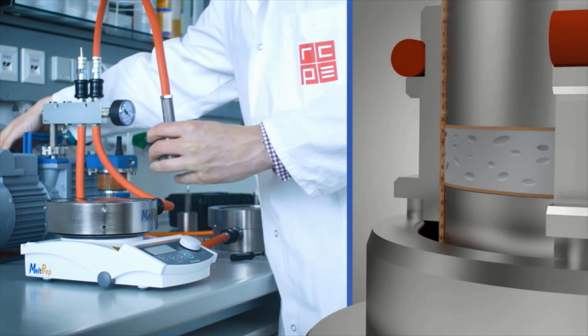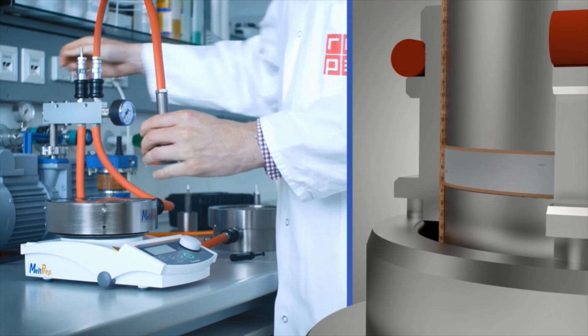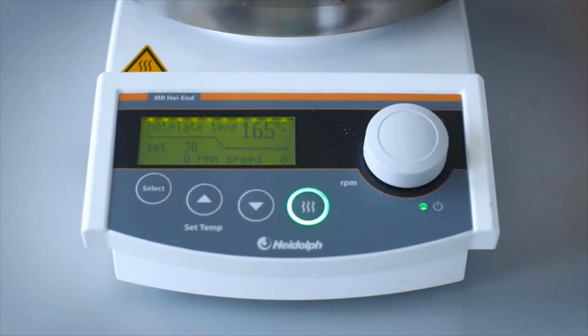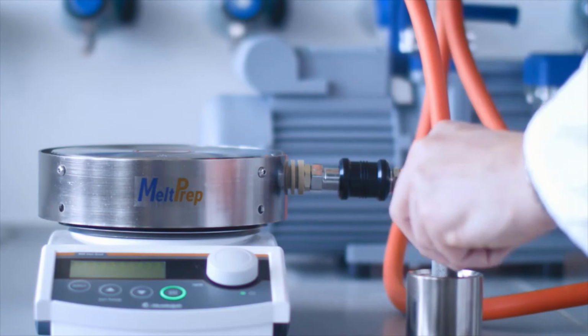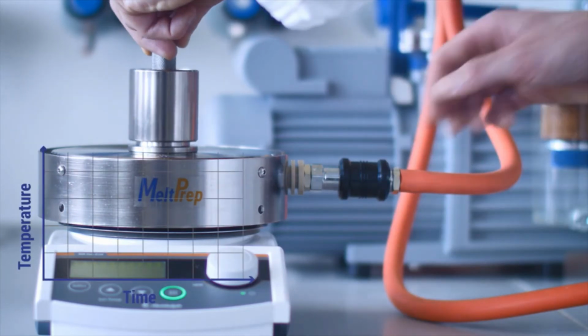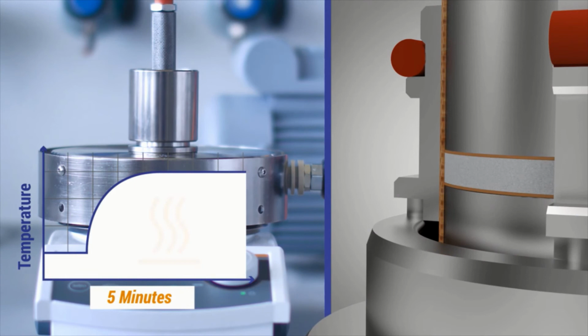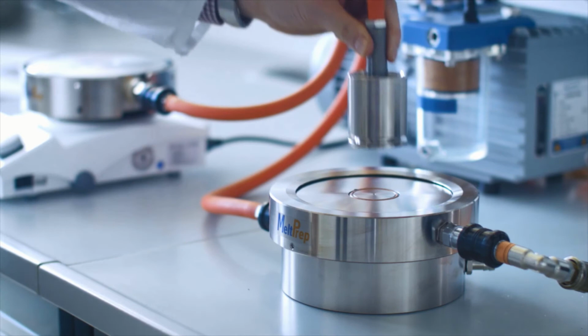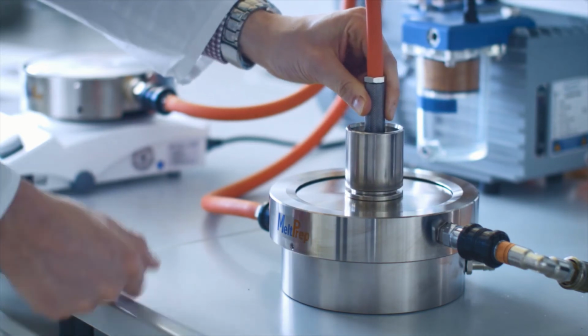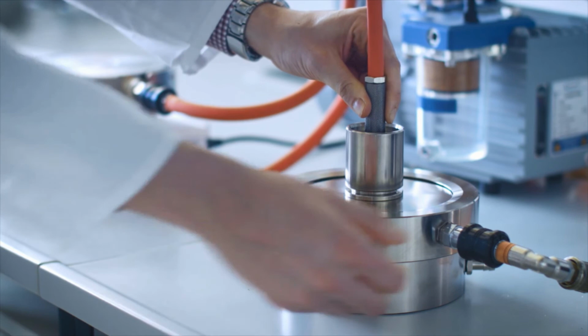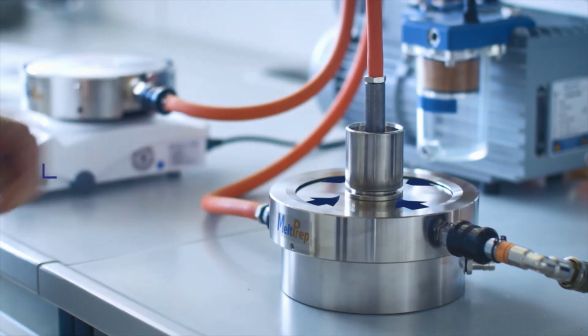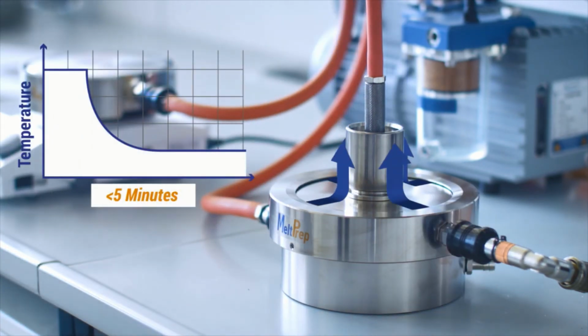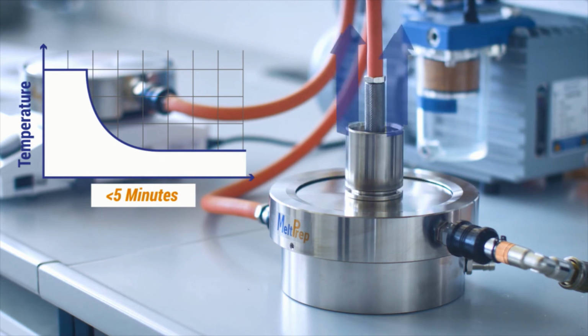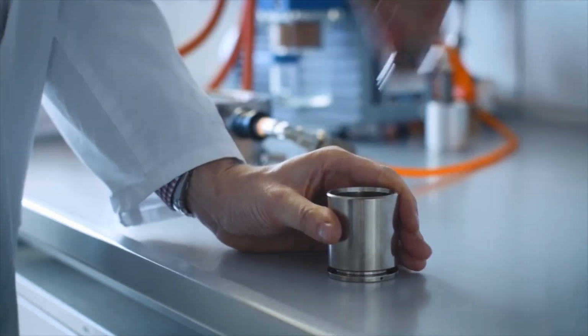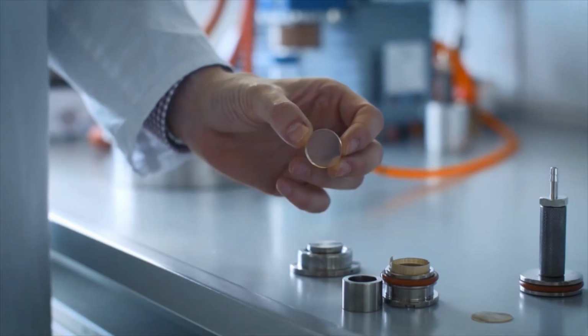The VCM tool is then connected to the vacuum unit. The air is drawn out from the chamber and the powder is compacted. Subsequently, the VCM tool is placed on the hot plate to initiate the melting. The powdery material forms a homogeneous melt. As a rule of thumb, this takes about 5 minutes. Once completed, the VCM tool is transferred to the cooling unit to cool it down to ambient conditions. Once cold, it is taken apart and the sample can be released with ease. The PTFE foils can simply be peeled off like stickers from the sample.